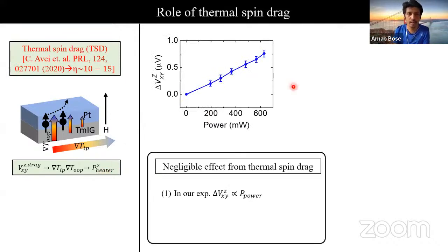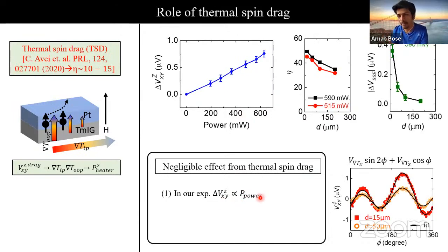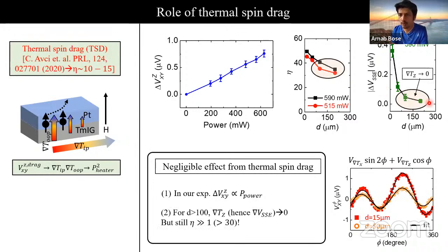In our experiment, we find that this voltage signal is very much linear with the heater power, giving us the impression that our data cannot be explained with this mechanism. And secondly, I mentioned that we could also understand how much the out-of-plane unintentional gradient is from this cos phi angular dependence, which we get from this expression. We find that as we go away from the heater, particularly when it is more than 100 microns, the out-of-plane thermal gradient is quite negligible.